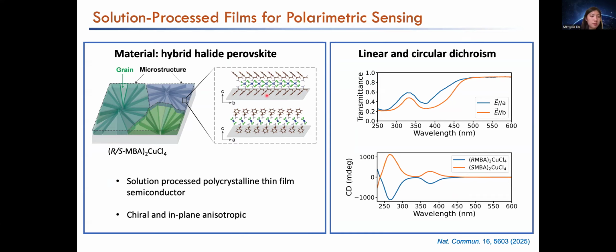So this gives it a very unique property called linear dichroism, which means when the light has a polarization along the a-axis versus the b-axis, the absorption of the material is different. And also, because this material is polycrystalline, each grain has a very different orientation. This means the a-axis of each grain is different. This generates a point-to-point variation.